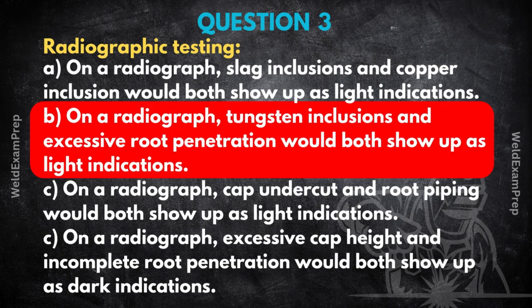All right, the correct statement here is B. On a radiograph, tungsten inclusions and excessive root penetration would both show up as light indications. Light indications. Why is that? It comes down to how radiography works fundamentally. You pass X-rays or gamma rays through the weld. Areas that are denser or thicker absorb more radiation. Less radiation gets to the film or detector behind it, so those areas look lighter on the radiograph image. Okay, denser or thicker means lighter image.